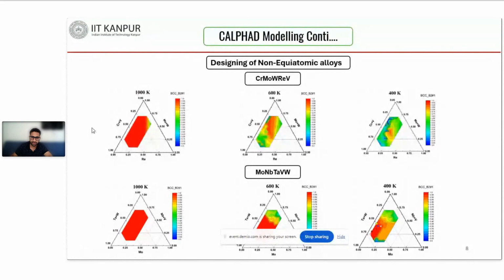Now if you see that at 1000 Kelvin, there are some alloys, I think 82%, showing a single phase structure. But when you go to the lower temperatures, 600 Kelvin and 400 Kelvin, there are very few alloys, or I will say no alloy, showing a single phase structure.